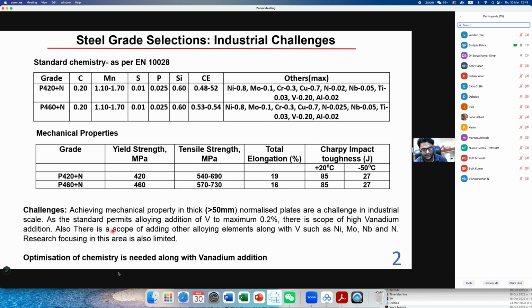So the challenge is achieving mechanical properties in this range, especially yield strength in greater than 50 mm thickness normalized plate, which is very challenging in industrial production. In this grade we have vanadium up to 0.2% maximum. So we are trying to add vanadium and get these mechanical properties in the normalized condition. Also, there are other alloying elements which we will be trying further.